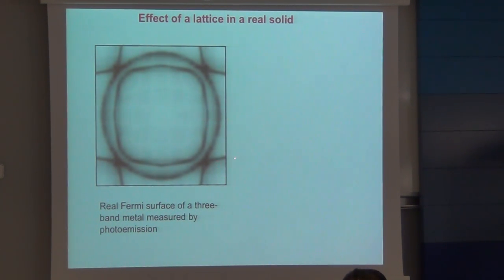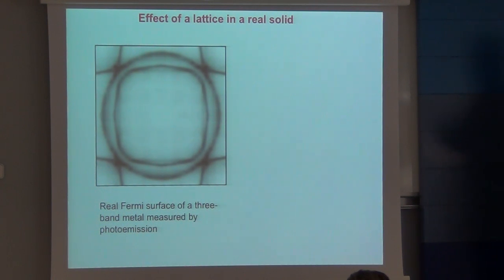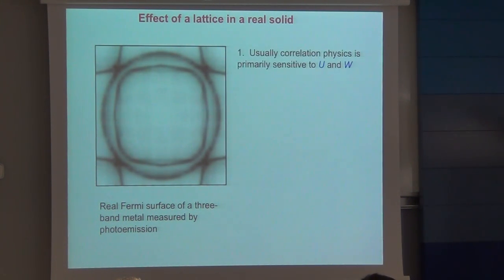and nowadays we can take almost any solid and do a photoemission measurement on it, and we can measure the Fermi surface, and the Fermi surface that we measure is going to be taking into account not just the lattice potential but also the electron-electron interactions. So we're highly used to thinking that that many-body Fermi surface that we've measured is going to be affected by the physics of correlation. And we're all used to the idea that we need to be thinking carefully about the electron-electron interaction energy U and its relationship with the electron kinetic energy W.